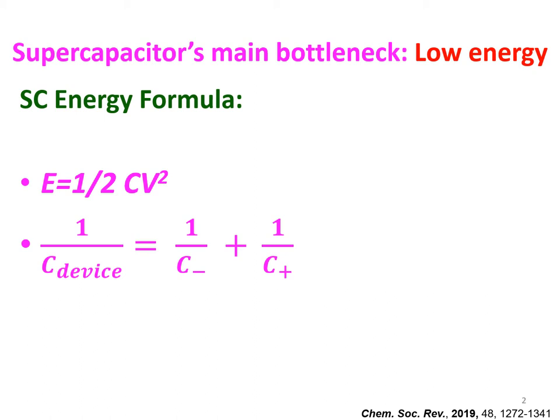There has been a lot of progress in the field of the positive electrode, but the low capacitance of negative electrode material severely limits the device capacitance. The most efficient negative electrode materials are carbon-based materials that operate based on the EDLC mechanism, and their capacitance barely exceeds 300 F per gram. Considering that pseudocapacitive materials provide significantly more capacitance than EDLC, development of pseudocapacitive negative materials is very important. So, what we need to do is to increase the negative electrode capacitance.